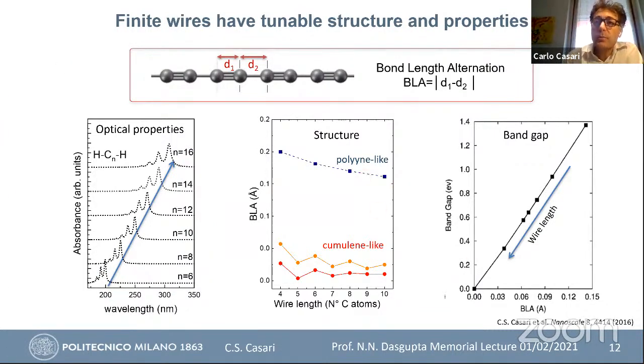And a structural parameter that is able to describe what happens is the bond length alternation, or BLA, that is the average distance between one bond and the other one. So for example, in the polyyne structure, so the alternated structure, this BLA is larger, while in the cumulene, the equalized structure with all double bonds, it should ideally be zero. But of course, in a real structure with terminations, as you can see here, the polyyne has the BLA at this level, while the cumulene is approaching zero, but is not exactly zero. This is because it's not ideal and infinite, but the termination plays a role.